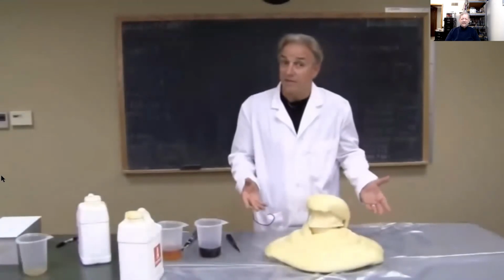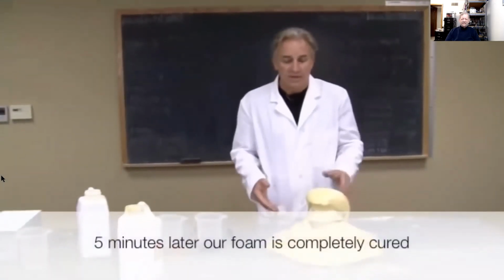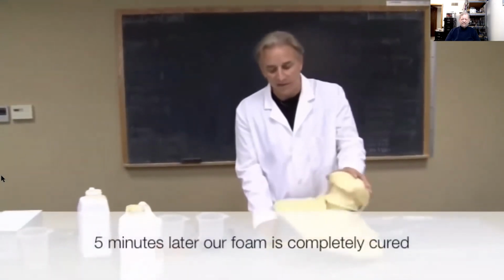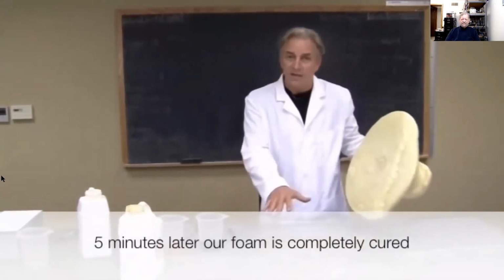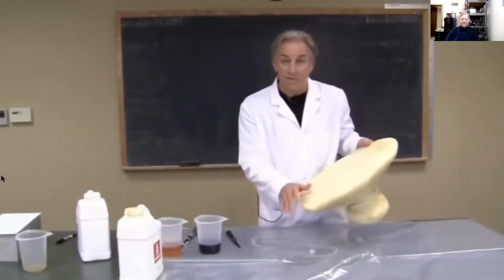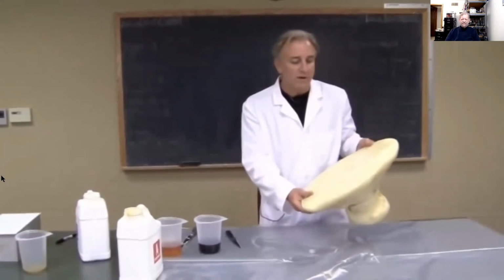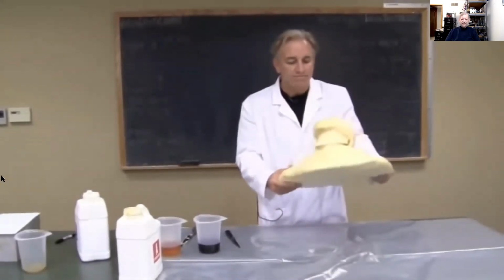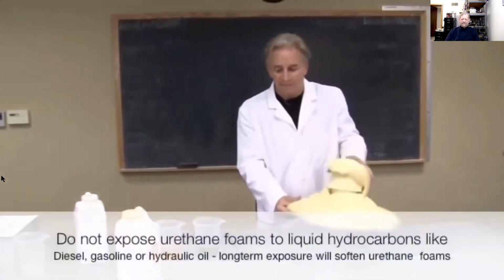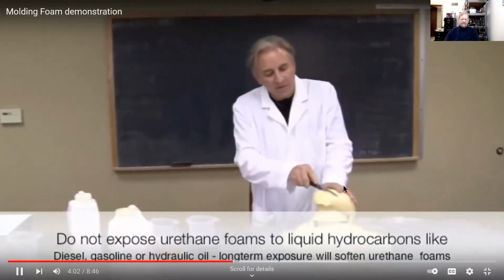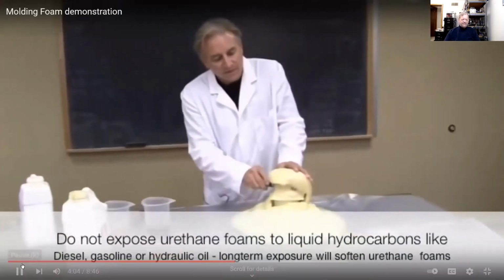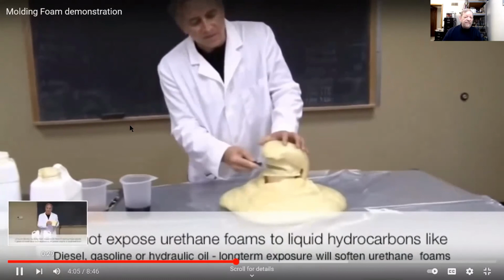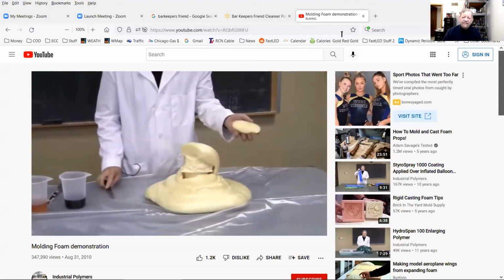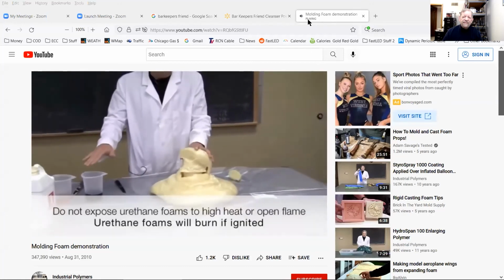Well, it's only been about 5 minutes since we initially mixed our foam, and you can see it's pretty well set. It doesn't stick to polyethylene or polypropylene plastics, so common garbage bags work quite well as a barrier. As you can see, it's durable and fairly lightweight. As we mentioned earlier, it's easy to carve and sand. The integrity of the foam gets better the more the liquids are mixed.